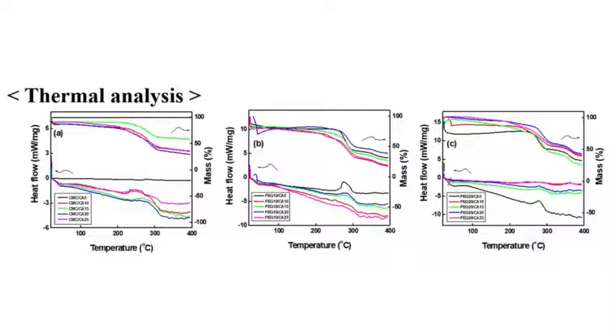DSC and TGA studies were performed with temperature up to 400°C at a heating rate of 10°C per minute. Significant mass loss corresponding to decomposition, evaporation, and removal of by-products was observed in the temperature range of 210 to 360°C. In particular, a dramatic decrease in mass loss was observed in the cross-linked CMC hydrogel compared to the non-cross-linked CMC.